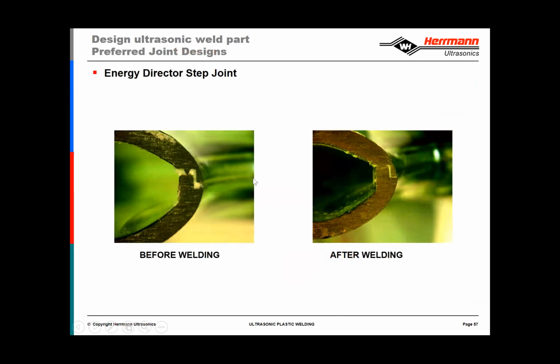Here's an example of an energy director on a part that we welded. You can see that this is a rather small part, and for that reason, the shape of the energy director is in the 60-degree configuration. Before welding and after welding, you can see that the melt was contained and that we have a nice solid bond between those two surfaces, an almost imperceivable line between the two parts that were welded.